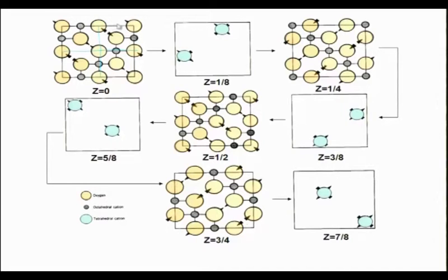Instead of keeping these empty and these empty, you shift the octahedral sites by another vector in the 110 direction. So you can see that this layer is now empty, this row is filled, this row is empty, and this row is filled. And then again you go to the tetrahedral plane, you rotate the tetrahedral interstices position. Now the tetrahedral sites which are filled are those which are along this axis.